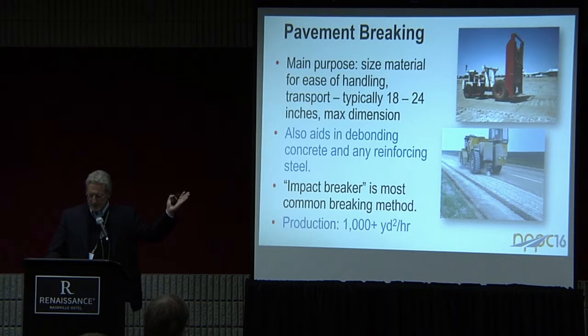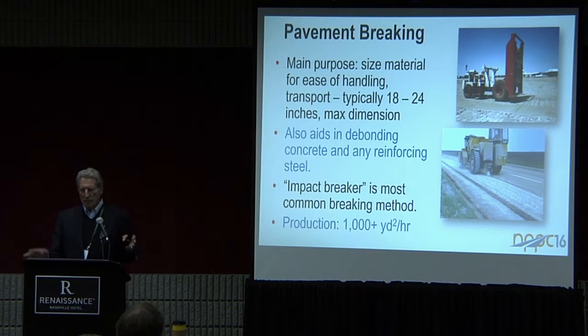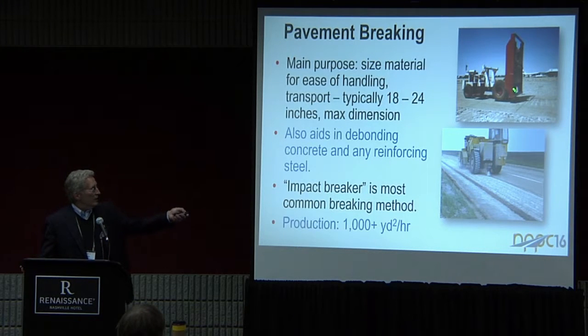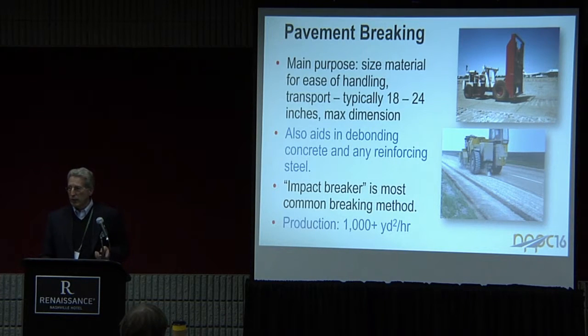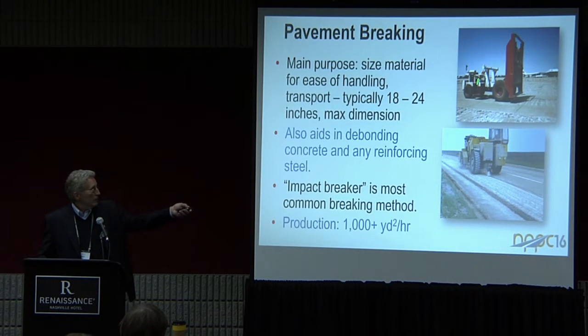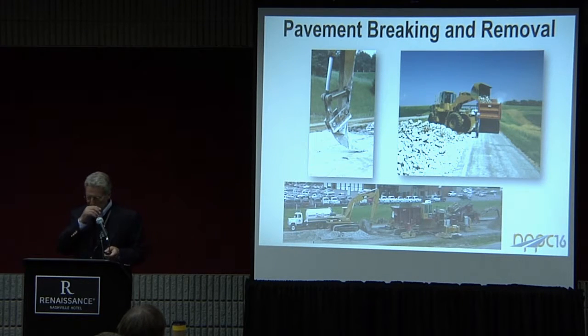The breaking processes, the main purpose of breaking the material is either to size it for ease of removal and handling, typically 1.5 to 2 foot top size. Also helps to break the stuff away from any steel that you might have in place there, particularly if you got CRC or jointed reinforced pavement. We see these guillotine hammers and impact hammers being the most common approach. Do see, if we're rubberizing it in place, the resonant pavement breakers like you see there, and you can get 1,000 square yards per day or more out of the drop hammers, and quite a bit more than that out of the resonant breakers. So pretty good production.